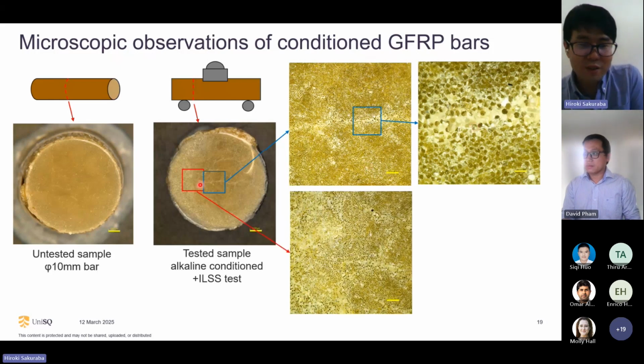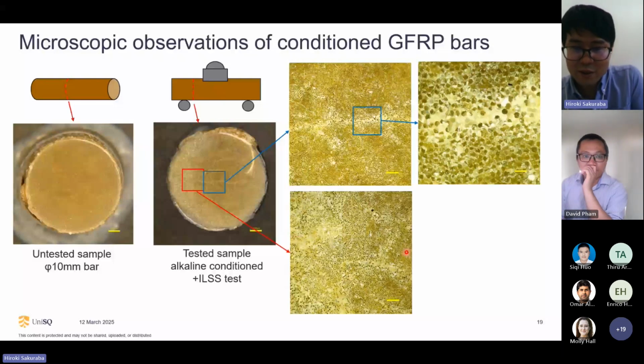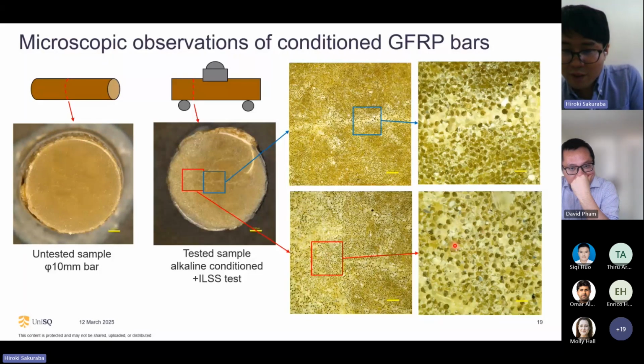In another example, if we look at this area, we can see a damage boundary. This is the alkaline affected area, but this is not the alkaline affected area. So we can observe the difference. At higher magnification, we can see the resin is damaged, and also the fiber filament is damaged. So by using low magnification to high magnification, we can see the damage position, and we can also see the damaged component of glass fiber, resin, and fiber-resin interface.